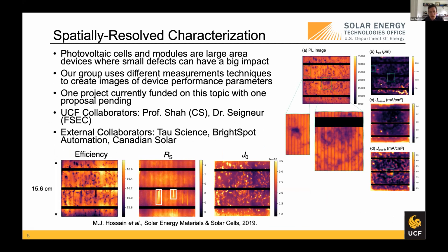So one of the things that we do is we use innovative measurement techniques like photoluminescence and electroluminescence imaging, where either we shine light on the solar cell or pump current into the solar cell and look at how it re-radiates light of a different wavelength. And that luminescence at each pixel, we can attribute using some different calibration techniques to a specific voltage. And so what we do is we treat every pixel as kind of like a parallel connected diode within the solar cell. And then we can solve for these different circuit parameters that typically you only measure at the solar cell level.